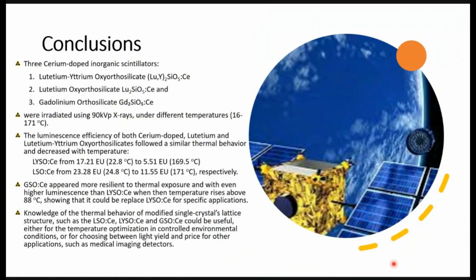So, as a conclusion, we can say that in this study, 3 cerium-doped crystals were examined. The two oxyorthosilicates with lutetium and lutetium-yttrium appeared with a big reduction in their luminescence efficiencies, whereas the much cheaper gadolinium crystal appeared to be robust with increasing temperature and with even higher luminescence efficiency values than the lutetium-yttrium. This is of importance when we need to construct a cost-effective imaging device that will be used in higher temperatures.